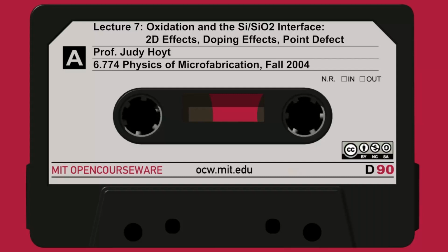Even the nitride itself is pushing down on the oxide, and in order to lift this nitride layer, the oxide has to do work. So there's definitely stress buildup in these regions, near corners or on curved surfaces. And that slows down the oxidation rate.